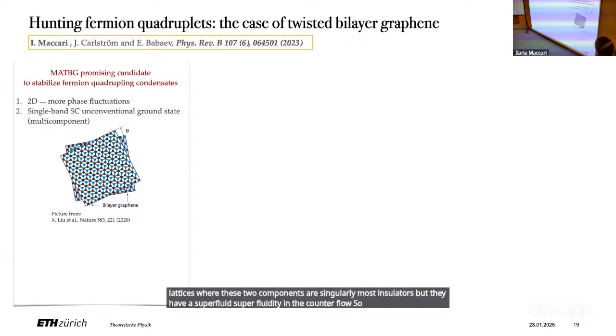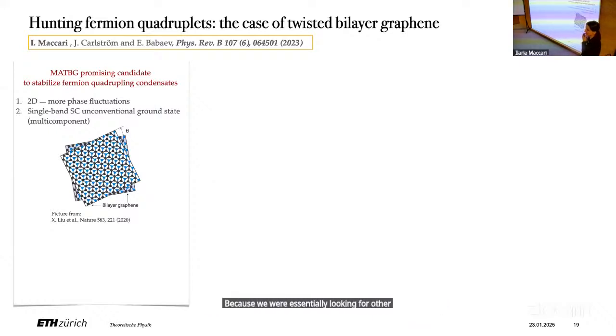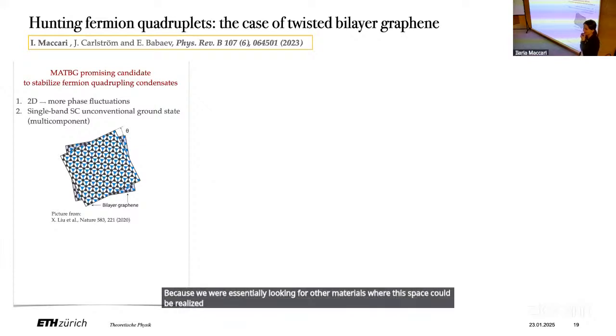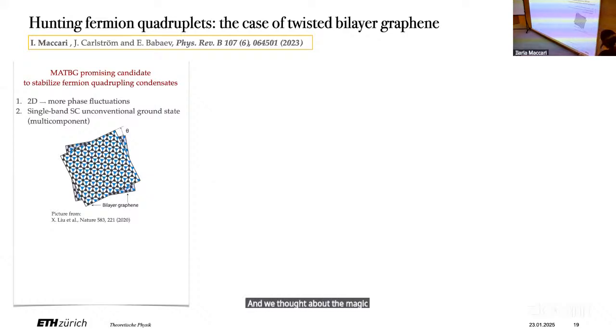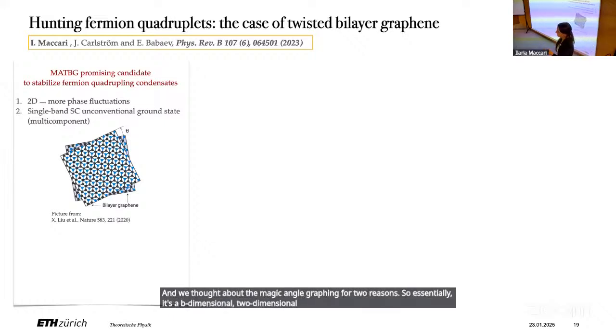So just to conclude, I would like to present you our last investigation, if I have time, because we were essentially looking for other materials where this phase could be realized. We thought about magic angle twisted bilayer graphene for two reasons. It's a two-dimensional system, and it's known to break multiple symmetries, so it's most likely multi-component. So it has the ingredient we needed. The two-dimensionality also is important because, of course, phase fluctuations are more important.